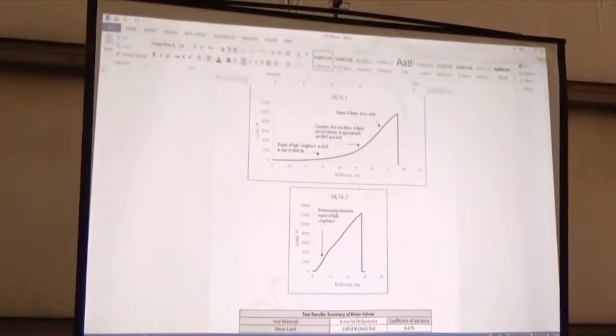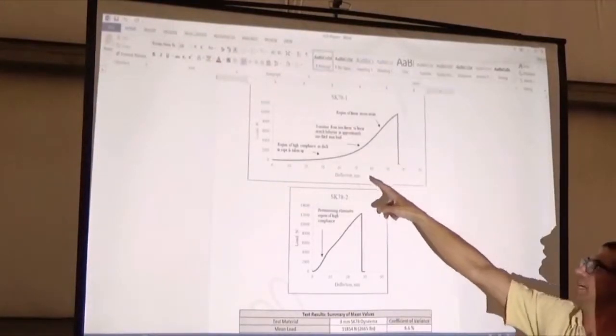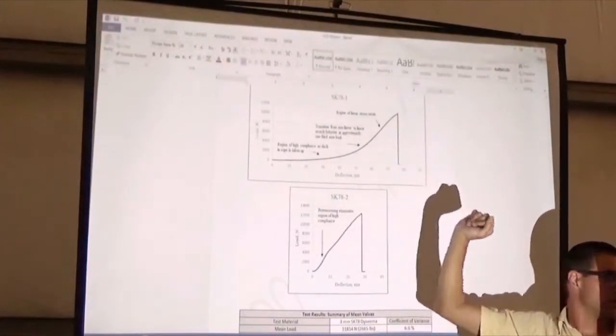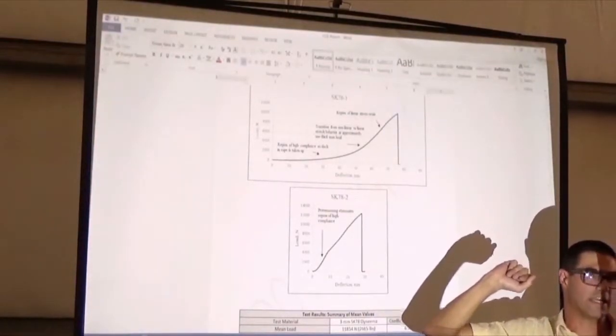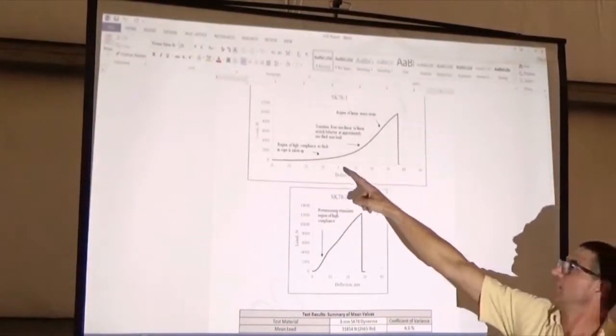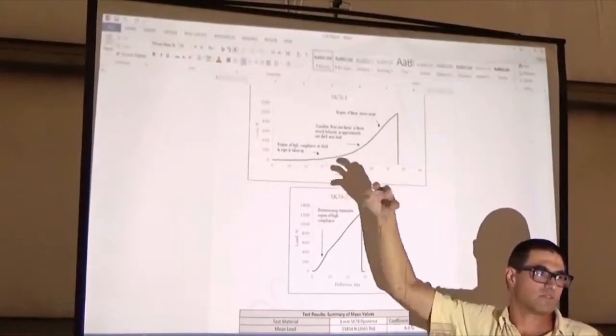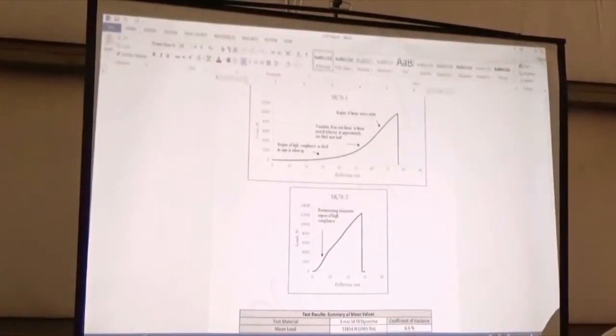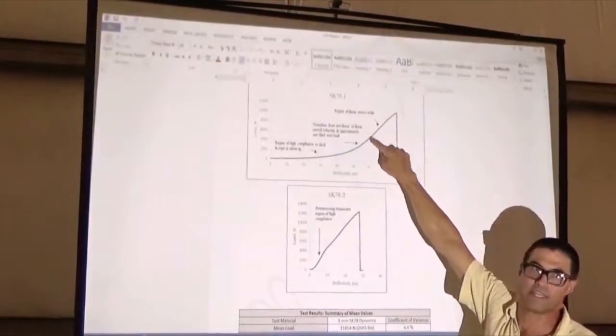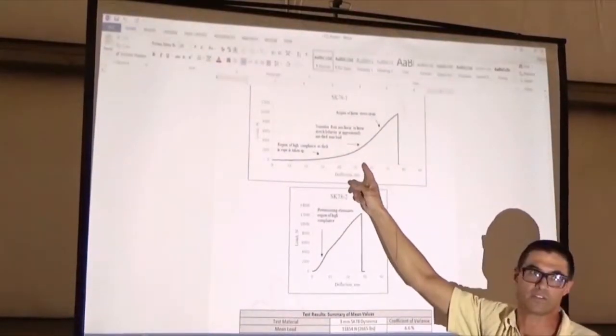I then looked at Dyneema, and I talked with a bunch of kite makers and different folks, and they recommended which Dyneemas to use. So I looked at something called SK78, and the first test that I did, this was it. And I was like, holy shit, this stuff stretches like crazy, I can't use it. So you've got a lot of compliance, and a lot of that compliance is in the splice and in the rope itself kind of getting taut. And then you finally reach this linear region, but that's after a lot of stretch.